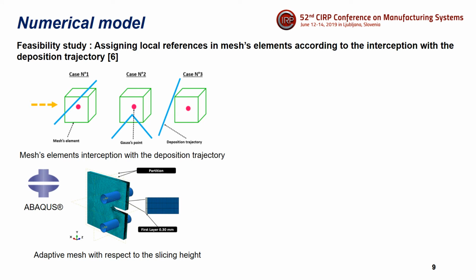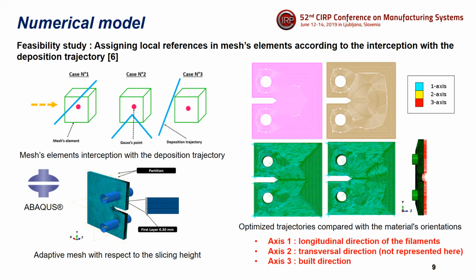A feasibility study was done, which consists of reproducing the printing trajectories inside a finite element model by assigning local references in mesh elements according to the intersection between the deposition trajectory and each element face. As presented in the figure here, this method was successfully applied on a CT specimen and both principal directions are well reproduced.